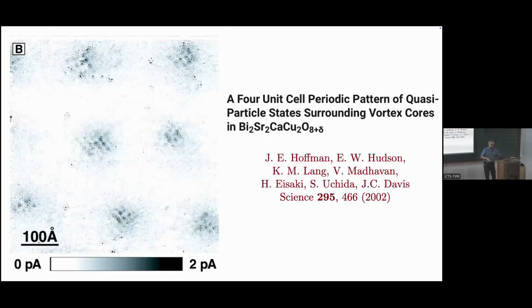On the overdoped side, you can solve the Bogoliubov-de Gennes equation for a d-wave superconductor, and that predicts what's now called the Wang-MacDonald peak as a function of energy at the core of the vortex, and that's seen beautifully on the overdoped side. But on the underdoped side, it's not seen, and what you see instead are period 4 modulations around each vortex core. So that's the summary of old and not so old data on the pseudogap. And if I have time, I'll tell you about our latest theory, where we think all of that falls into place.